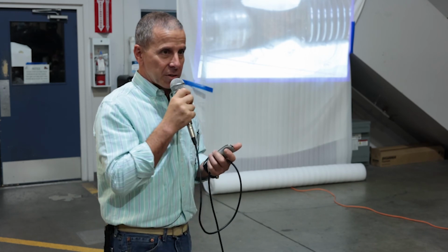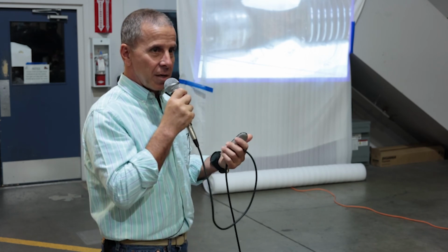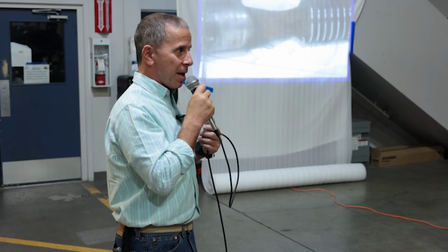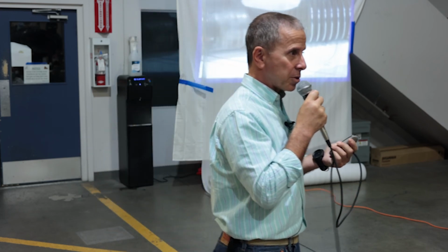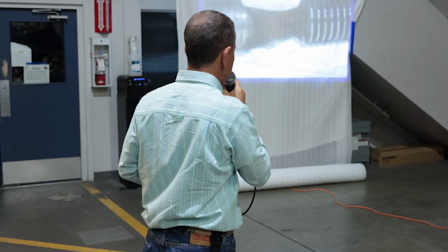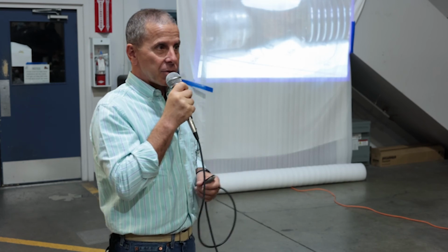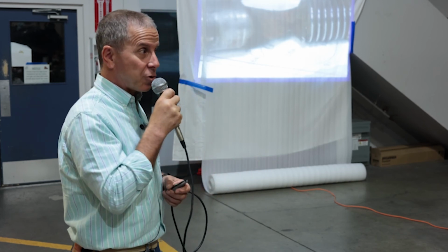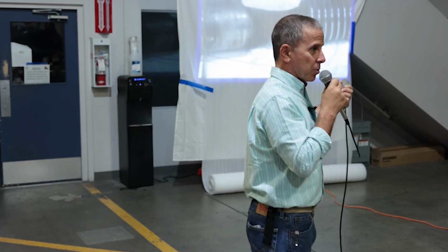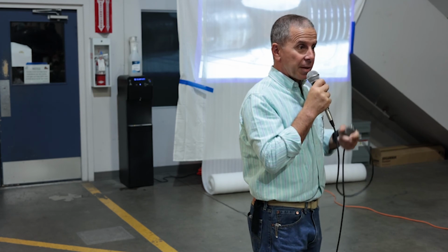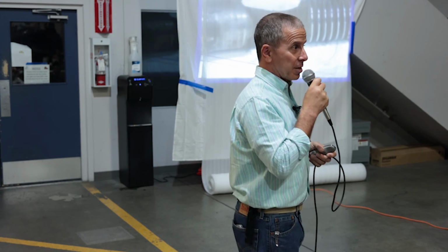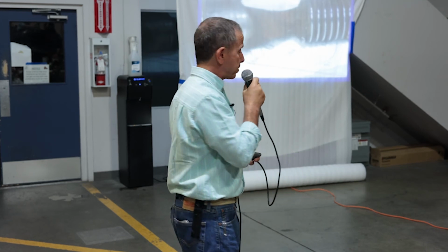The dangerous part of this scenario is the parts of the fastener you can see look perfectly fine. The head and the threaded end, the parts that are exposed to oxygen, are doing okay. But the part that's inside the area where it's passing through, a hull again in this case, is crevice corroding. That's a dangerous kind of scenario because upon inspection, everything looks fine. This fastener was actually attaching a propeller strut to the bottom of the boat, so a pretty high stress scenario and one that's really important, but we didn't know that it was a problem until it was removed.